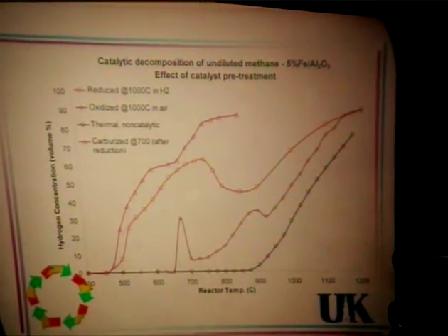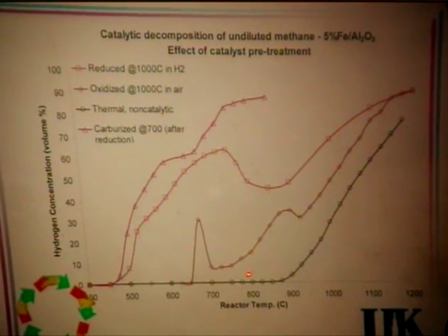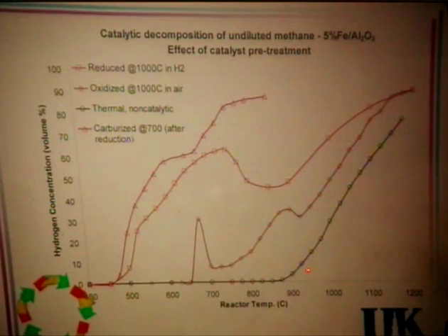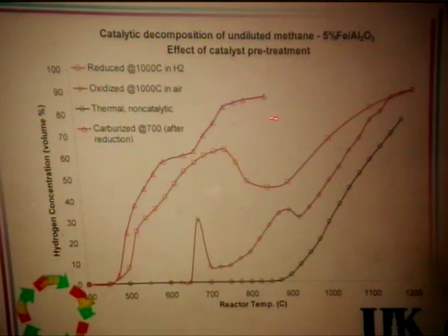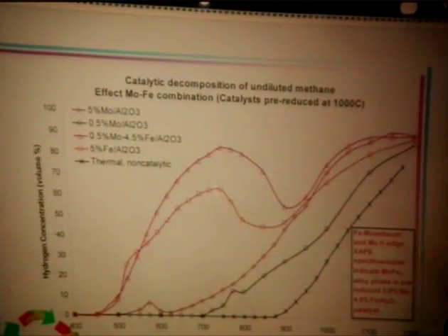Here is the 5% iron on alumina, and we have taken a run with the non-catalytic, that is, thermal cracking. Methane cracking starts above 900 degrees centigrade, whereas on the oxidized iron supported alumina catalyst it starts at lower temperature, but it's not very active compared to the reduced one or the carburized one. Overall, the carburized one showed better activity. We stopped the reaction here because of clogging of the reactor. It started developing back pressure. Overall, the carburized catalyst shows better performance than any other catalyst on 5% iron and alumina.